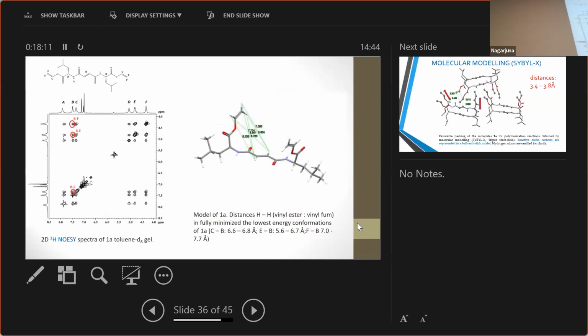Also, we do some 2D NMR NOESY spectrum, and we see some interaction through space between the end vinyl groups and center fumarate groups. It is here, here, and here. It is impossible in one molecule. We do some molecule modeling and obtain the geometry of this molecule. It is too far; these distances are about 7 angstroms, and it is not visible in NOESY spectra. So we conclude that this interaction comes from a second molecule, and this connection shows intermolecular association.